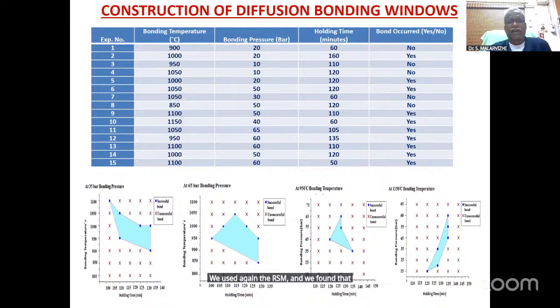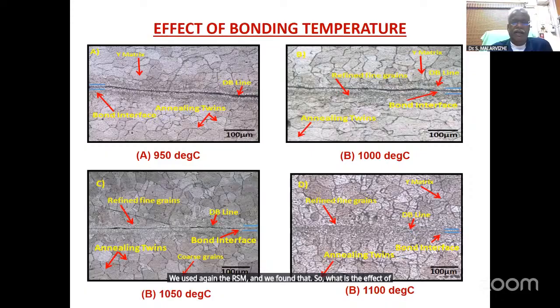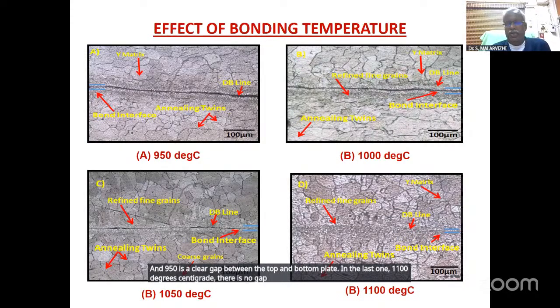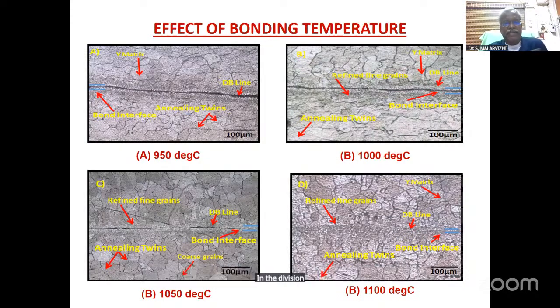So what is the effect of temperature? If you see the 4 different microstructures at the 4 different temperatures we used, at 950 there is a clear gap between the top and bottom plate. In the last one, 1100 degrees centigrade, there is no gap. It's completely closed in the diffusion bonding. So temperature has an effect on that. So we have to choose the right temperature.